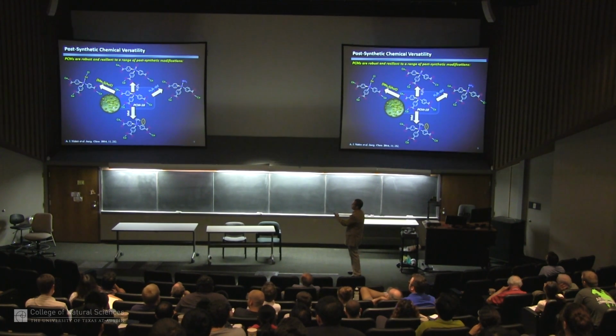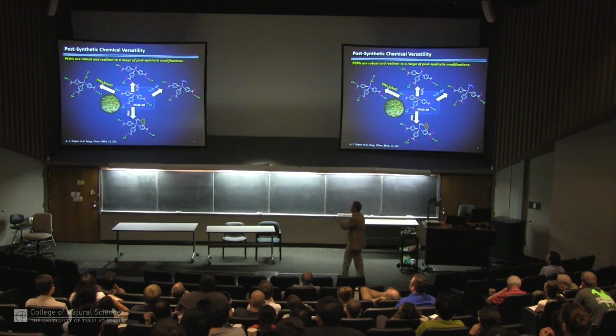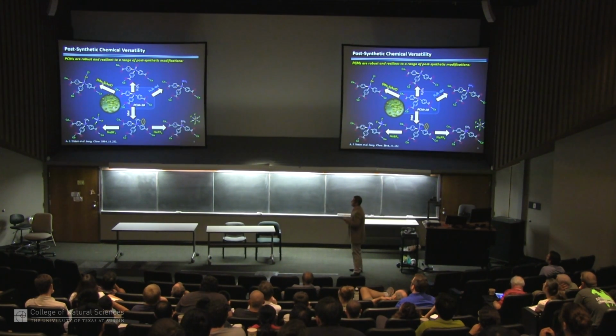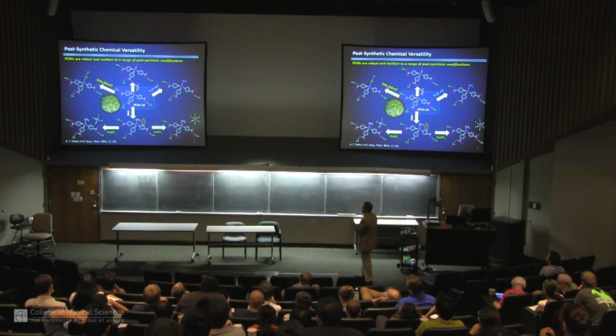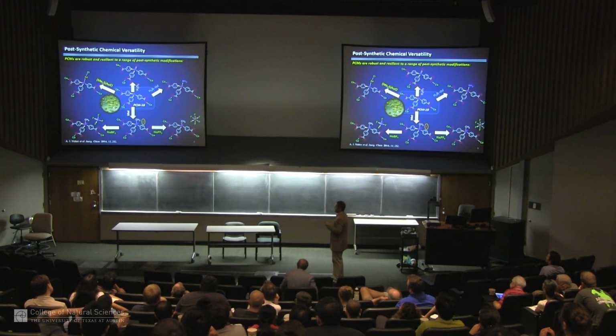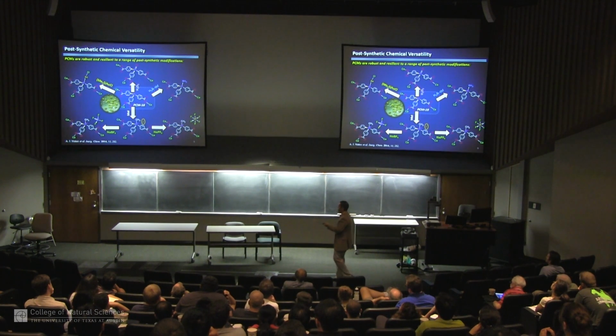This is just a small map of some examples. To put metals on the phosphines, to oxidize them post-synthetically, to protect them. We can even do this methylation. These all happen at room temperature. And whether you're familiar with this chemistry or not, the interesting thing here is that if you make one of these p-alkyl head groups, we incorporate a counterion to balance the charge. And now we have an easy way to do anion-cation exchange in the materials. And so we can exchange, in this case, these anions and put fluorinated anions inside the pores, which gives us non-stick character. So again, the same one material has given us access to 7 or 8 new materials.